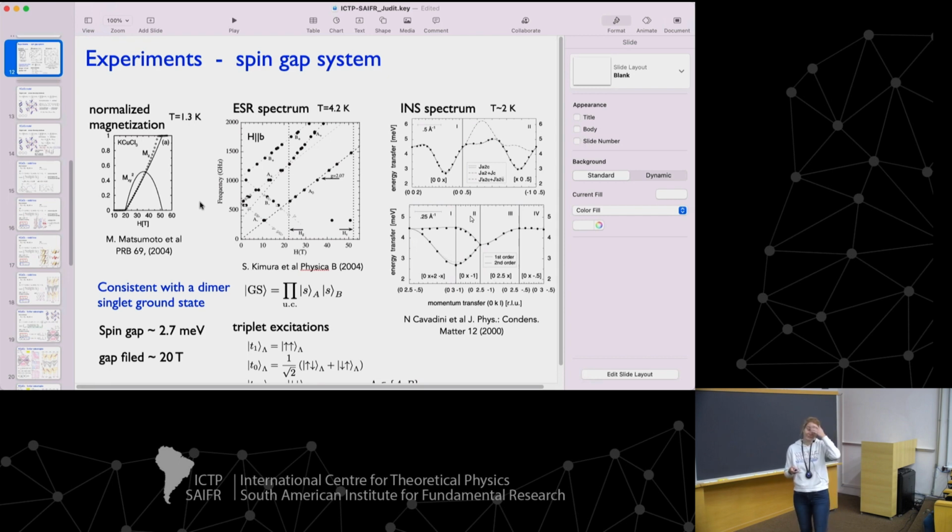That's exactly the reason why the thermal Hall is not quantized, right? Because you thermally fill these bands, and you would probably just have contribution from the bottom of the bands. And most of the time the Berry curvature is really located where you were supposed to have the degeneracy. So when you open the system, the Berry curvature will be close to the touching point and not at the bottom of the band. So these are very hard measurements to do, especially in the gapped system, because you need to be at higher temperature to actually fill the bands somewhat. Thanks for the question.